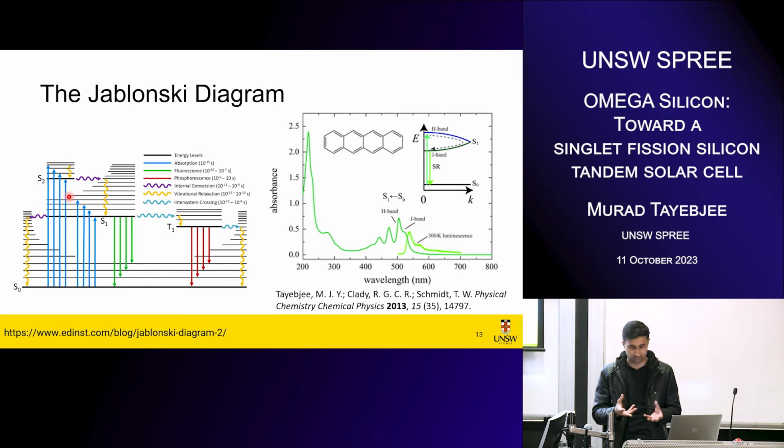These are the phonons inside your molecule, and that manifests itself in your absorption spectrum. So this is the absorption spectrum of tetracene, with these different peaks in your S0 to S1 transition. As you get to higher and higher energy, you have the S0 to S2 transition. All right? Similarly, you can get down from S1 to S0 via fluorescence.